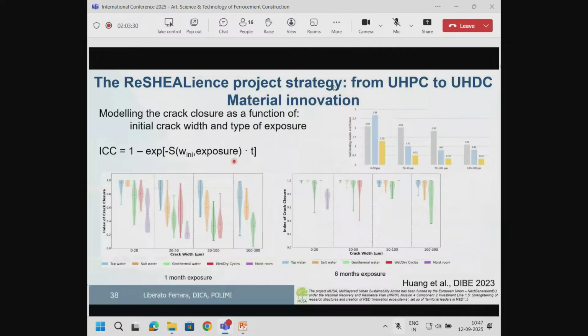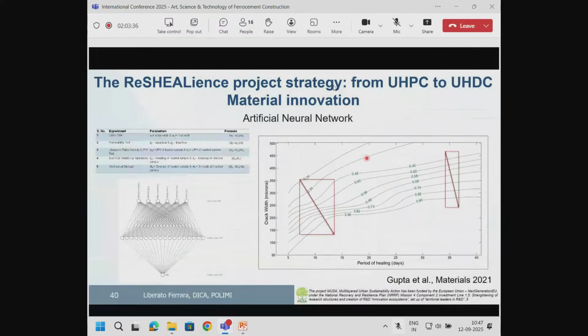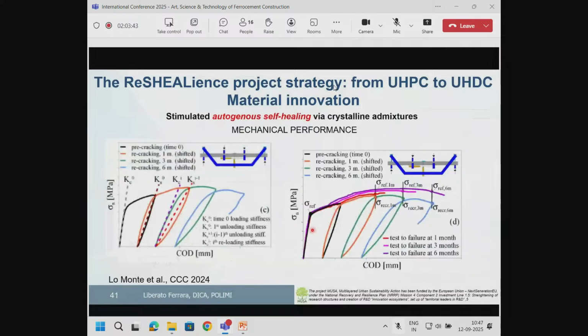artificial intelligence, neural network. We developed a crack closure kinetics index, which depends obviously on the initial crack width and on the exposure type, and developed also design charts in which, for example, we correlated the capacity of healing to crack width and to the period of healing. We validated the